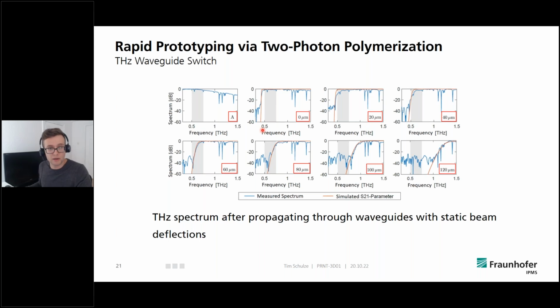So the spectrum I have been measuring is the blue line here. So this is really the stuff I have been measuring with my terahertz system. And the red one was the simulation of the transmittance of my waveguide. And we can see a very high degree of overlap between our FEM simulation and our result from our printed component. And so what did I do?